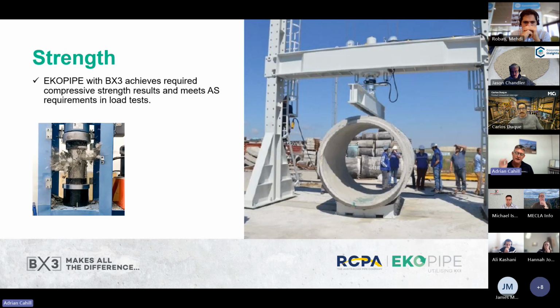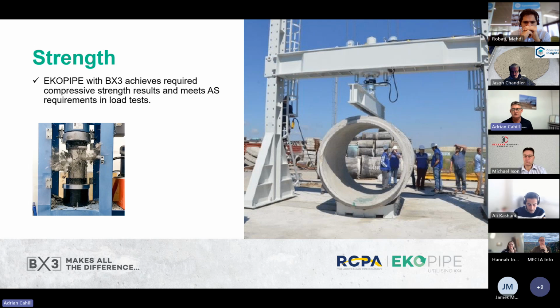Next. So I'll talk a little bit about some of the mechanical stuff. Obviously we do, well, not obviously, but we do routine concrete compressive cylinder tests, just a photo there. But more importantly, all manufactured concrete pipes undergo what's called a proof or ultimate load test, where we take a pipe, we put it under a large load tester, like this, and depending upon the diameter and the class of pipe you're making, the pipe has to carry a given load without developing a crack more than a certain width, and it has to carry an ultimate load without failure.